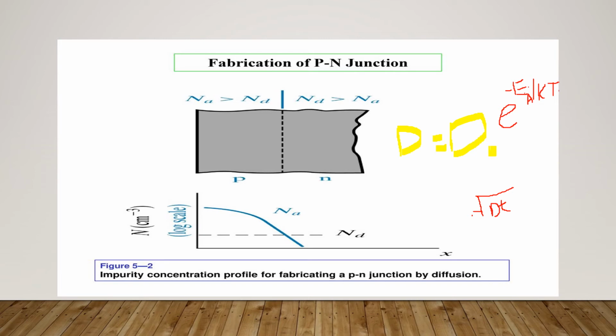The Arrhenius dependence of diffusivity on temperature explains why high temperatures are required for diffusion. Otherwise, the diffusivities are far too low. Since D varies exponentially with T, it is critical to have very precise control over the furnace temperature within several degrees in order to have control over diffusion profiles. The dopants are effectively blocked or masked by oxide because their diffusivity in oxide is very low.